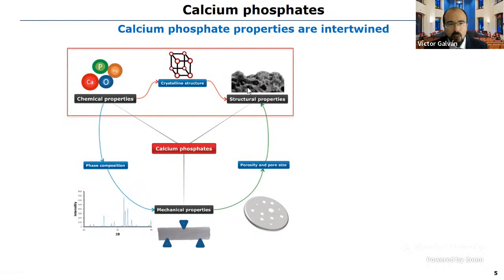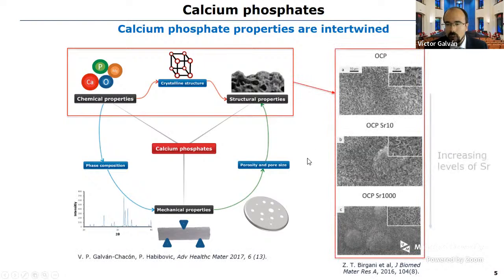For example, if we change the chemical properties of a calcium phosphate by incorporating an ion into the lattice, it can be a bioinorganic like magnesium or strontium, it will not only change the chemical properties, but it will also affect the structural properties, for example, the roughness of the surface. We can see this in this example in which 3 calcium phosphates were synthesized with increasing levels of strontium. And as you can see, it also affected the microstructure of the material.